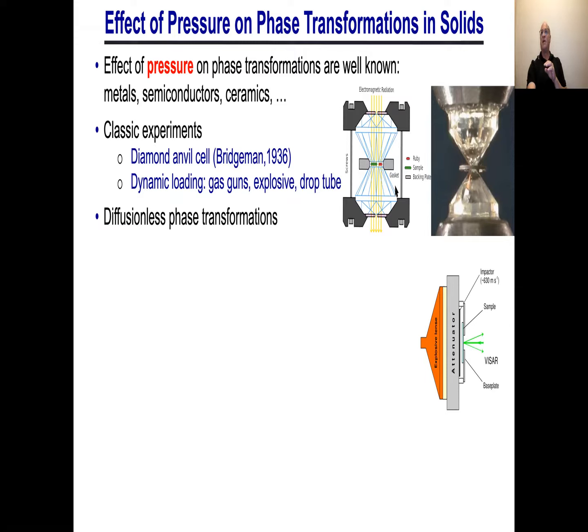Just point out a few things about this. So what happens is you squeeze on it, put a force on it this way by tightening the screws. There's a gasket that goes around here. You have the sample sitting in there, and there's usually little rubies in there which have a fluorescent line that shifts with pressure. And so by shining light or X-rays in there, we can understand the structure of the material and also measure the pressure. You can also do this dynamically, and people use gas guns or explosives like shown over here, or drop tubes. There are many ways to put on very high pressures. And even though these are dynamic experiments, I'm really going to be focusing on pressure for the moment. And we'll talk about strength issues later on.